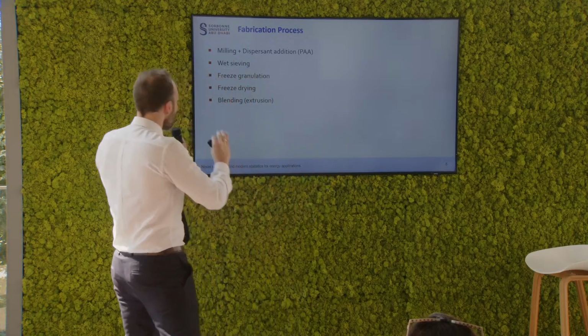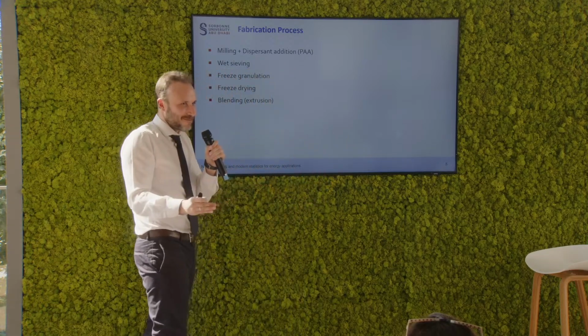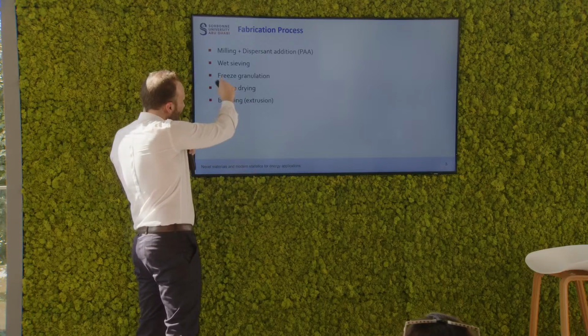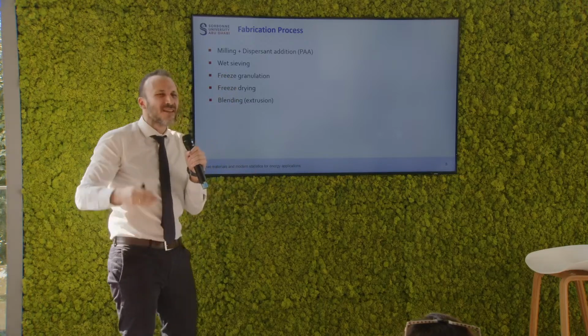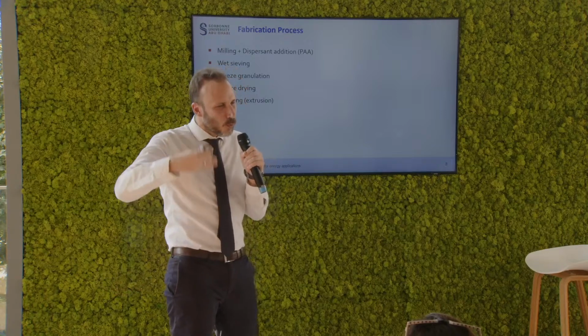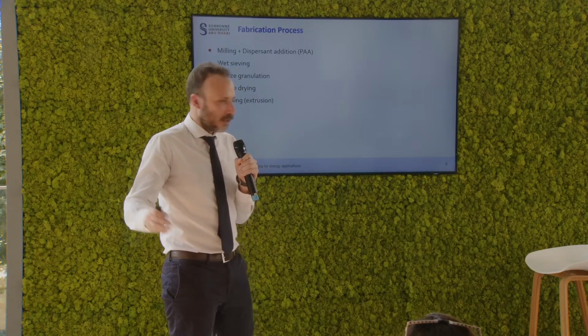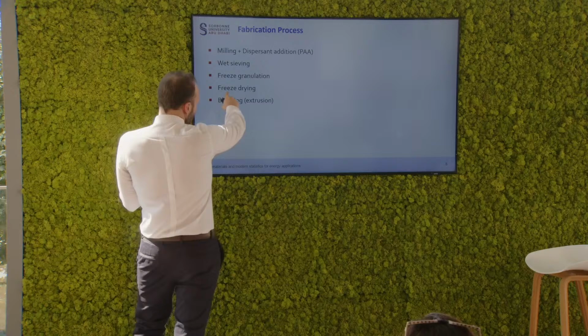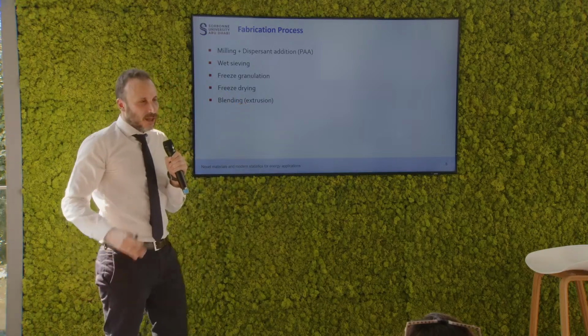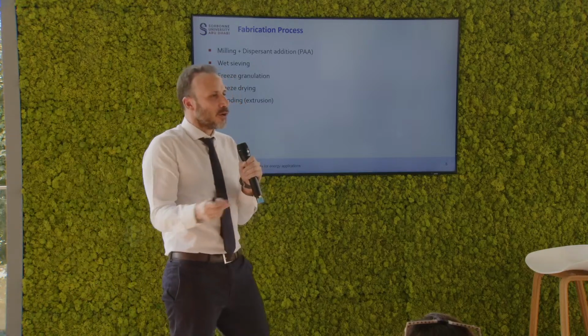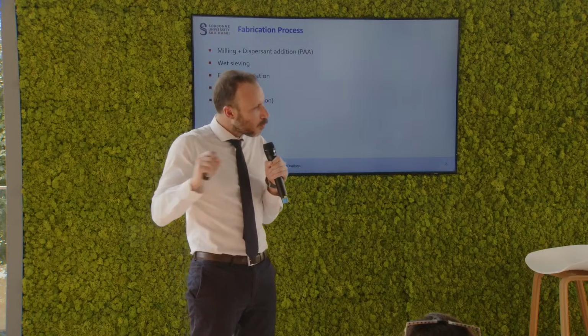But the most important thing is that they are extremely brittle now because they have been frozen at a state that is pretty much unstable. So having taken them from the wet sieving process, they might include some water. And you wish to remove that to improve your homogeneity. So what you do is pass them through a freeze drying process in which you regulate temperature and pressure in order to remove water molecules through sublimation.